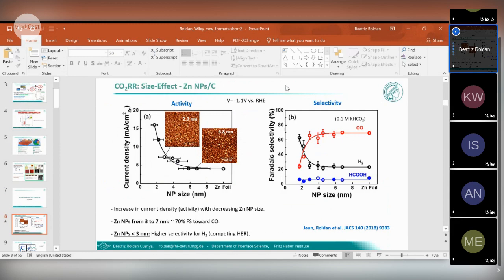We don't want to make hydrogen in this process. So something is happening here, and what we learn from comparison and from discussion with theorists is that on the surface of very small nanoparticles, in this case below 3 nanometers or so, you have a large number of low coordinated sites that bind hydrogen very strongly. Then you are not at this optimum that we want to have. If you have these conditions, you are not able to produce CO. You always favor the hydrogen evolution reaction. And in the case of copper nanoparticles or gold nanoparticles, you see the same thing. You always favor hydrogen for the very small nanoparticles. But this is not enough.